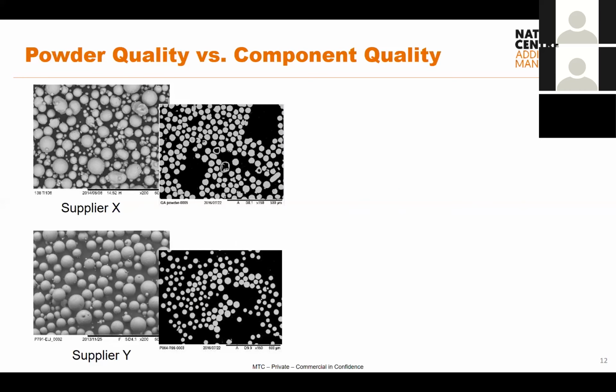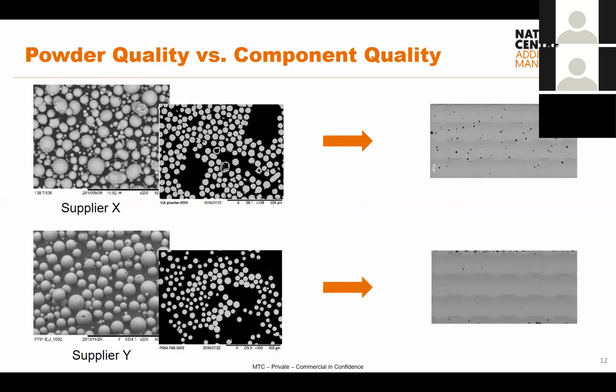Now, when we build parts, I don't want to try and say this is cause and effect, but when we build parts on the same machine under the same conditions, we see very large differences in porosity of the part. So with supplier X, you see substantially more pores within the microstructure than you do with supplier Y. That's not to say that supplier Y in this scenario is better than supplier X. It's just that we have the right processing conditions for supplier Y, whereas for supplier X we might not have. We could probably improve that microstructure substantially by modifying the melt parameters.